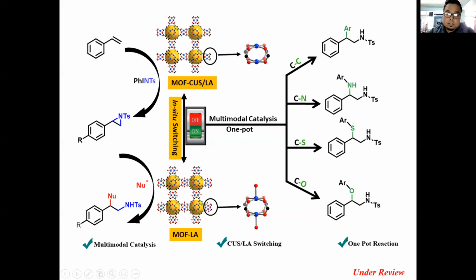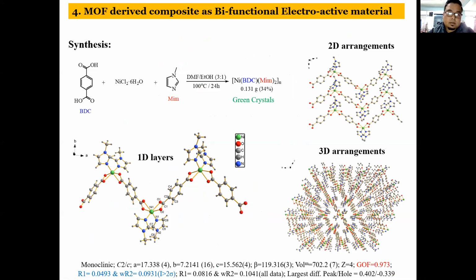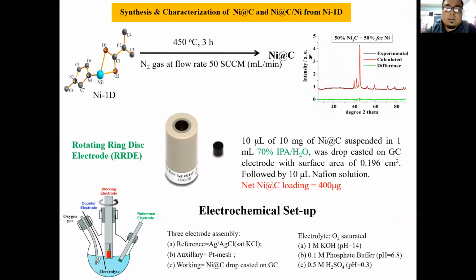Now the last example that I'll be showing is that we have derived some metal composites from MOFs that we have prepared and used them as electroactive material. What we did was we synthesized some one-dimensional 1D compounds containing nickel, and we converted them into composites. We converted this nickel 1D at high temperature and formed nickel carbon composites, which contain 50% nickel carbides and 50% metallic nickel.